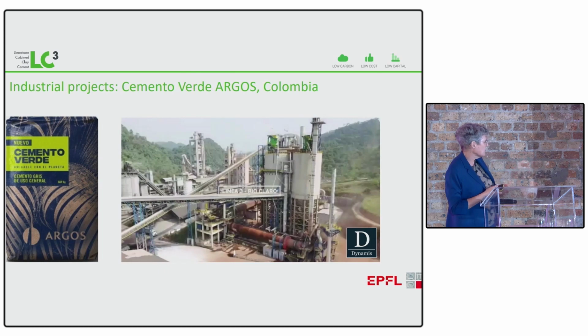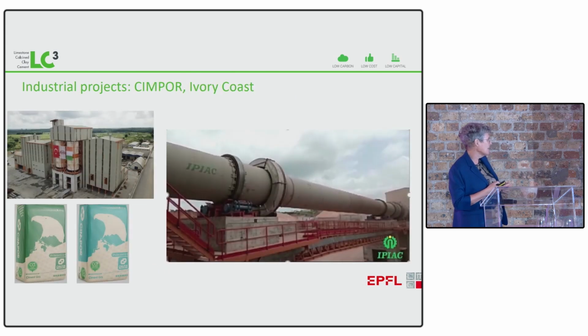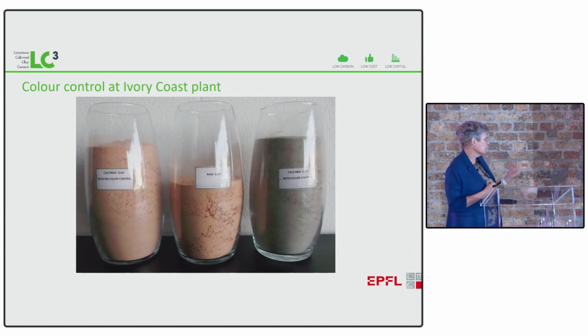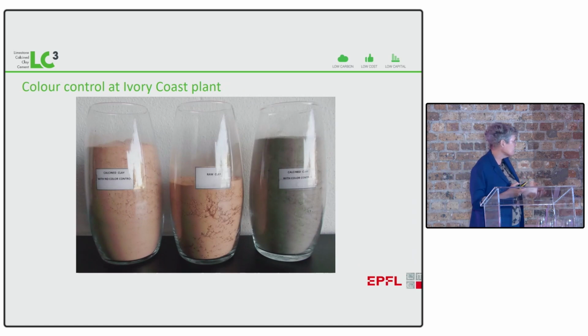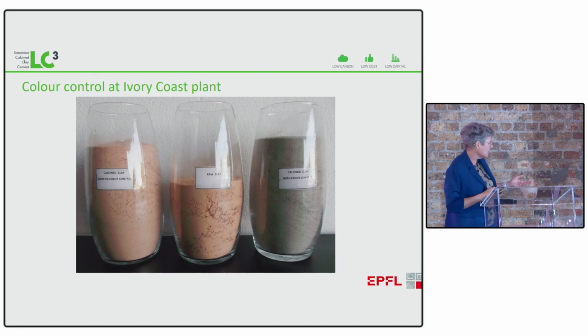This shows one of the first plants, which was set up by Argos in Colombia. This is another greenfield plant which was built by CIMPOR in Ivory Coast. What was particularly interesting in this plant is that they could demonstrate it's possible to control the color. Many of you know that cements tend to be reddish, and some people say, well, we don't want red cement. Well, if you don't want red cement, you can make it grey, which is good news.